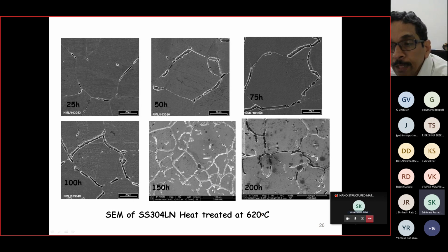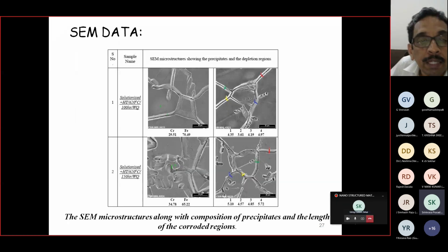So now I can say that chromium carbide has formed, but still I am not able to understand the magnetic properties, nor am I able to tell much about the size and morphology. So what I try to do is measure these things using the same SEM microstructures. I'm sorry that this particular microstructure is not very clear. I think the scale is about 20 microns over here, and the length scale is coming to be 4 to 5 microns.